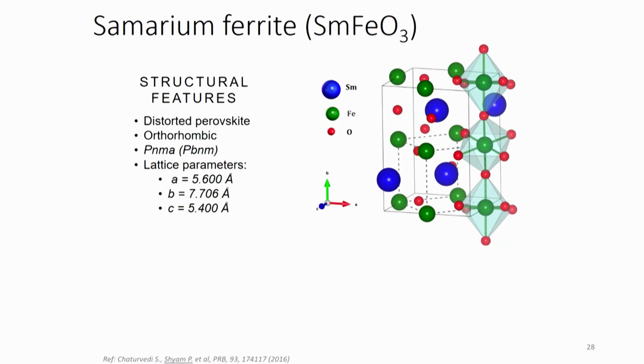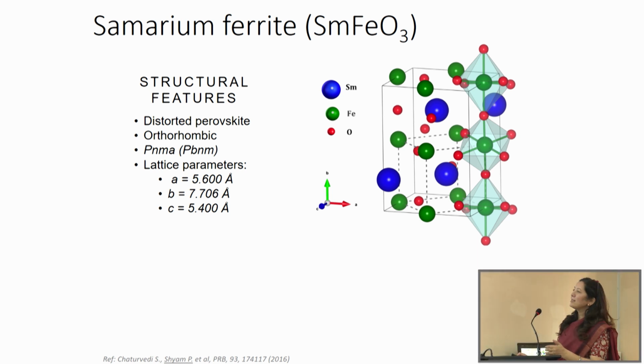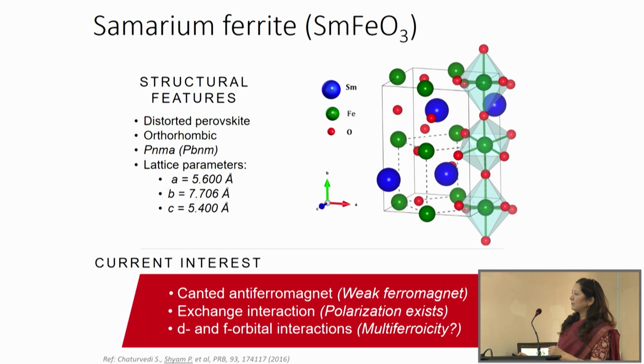This is the structure. It is a distorted perovskite. It is orthorhombic. The space group is Pnma, or it is also represented as Pbnm, and these are the lattice parameters. So we looked for whether a canted antiferromagnet exists or not. We looked for exchange interaction, we actually found it does exist, and D and F orbital interactions were seen. So we could say that there is a possibility of multiferroicity.